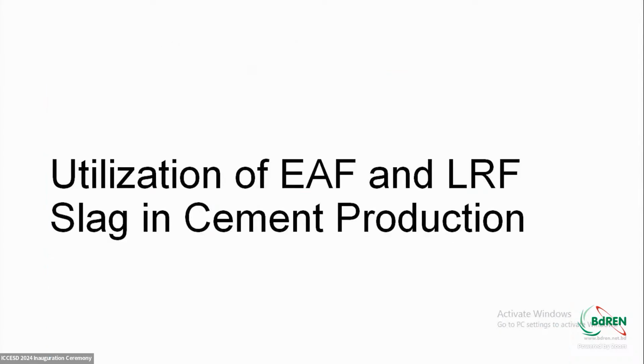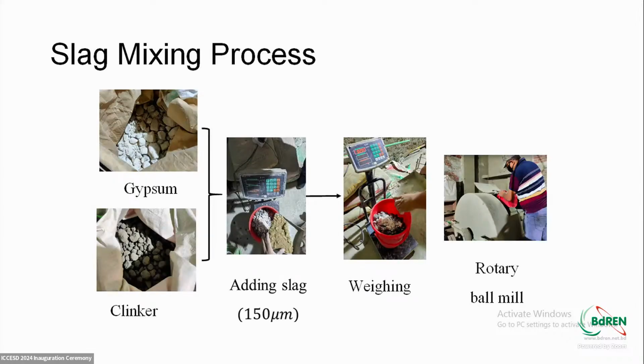Now we tried to utilize the slag, EAF and LRF slag, in cement production. The process was like this: clinker had gypsum added, then slag was added in powder form. Both EAF and LRF slag were pulverized, with particle size lower than 150 micrometers, and then added in different quantities depending on the mix design.